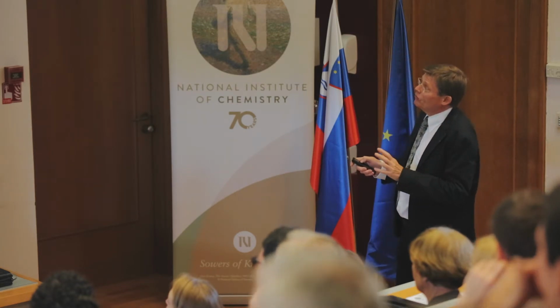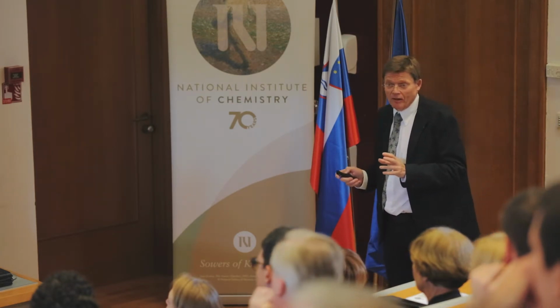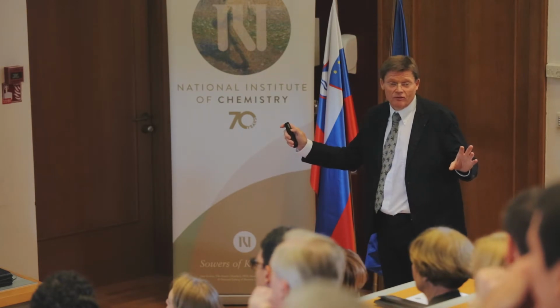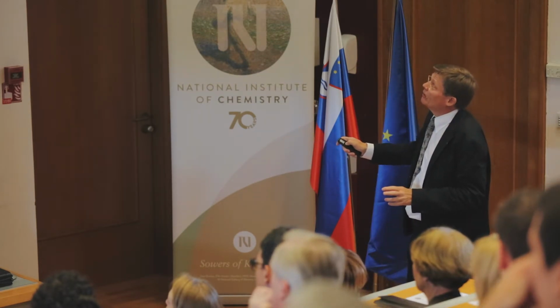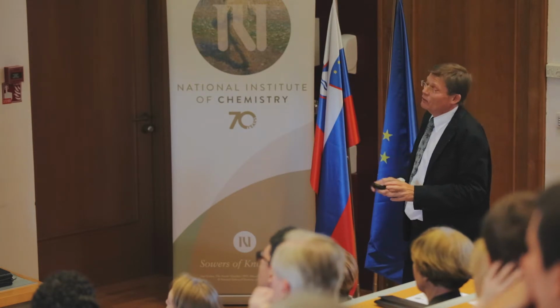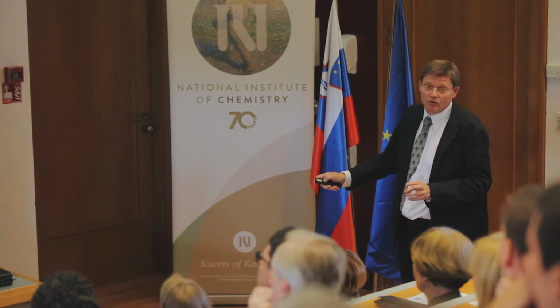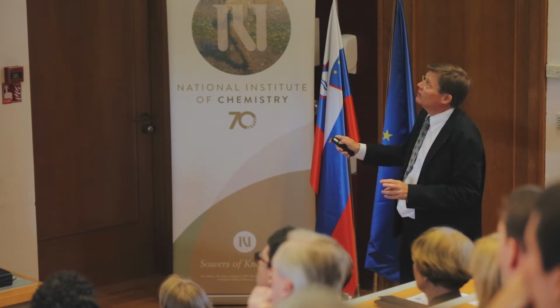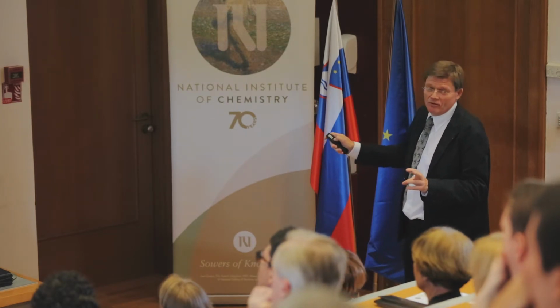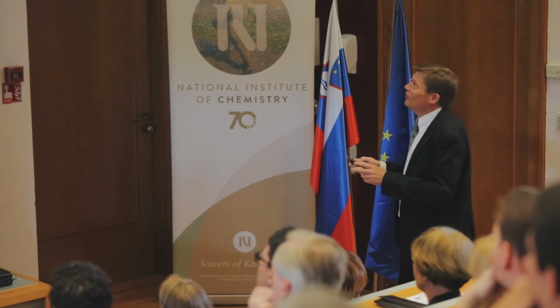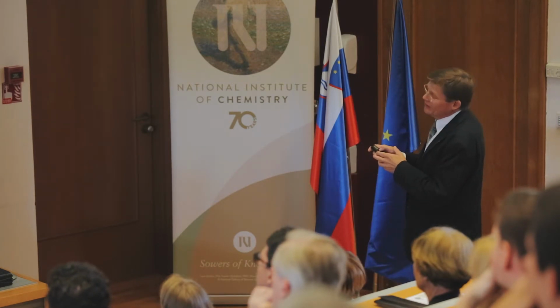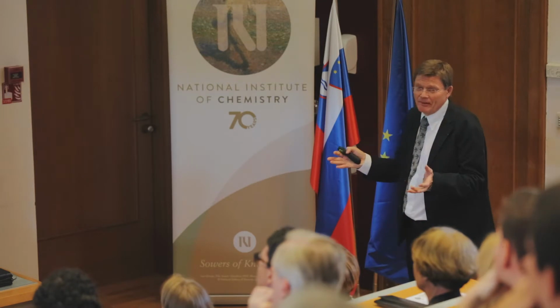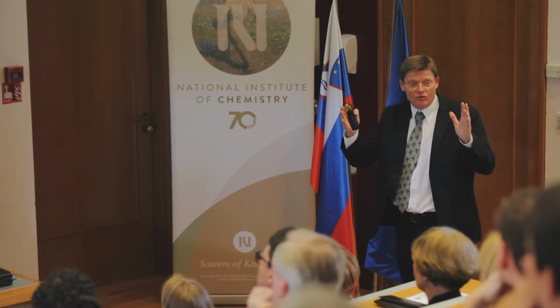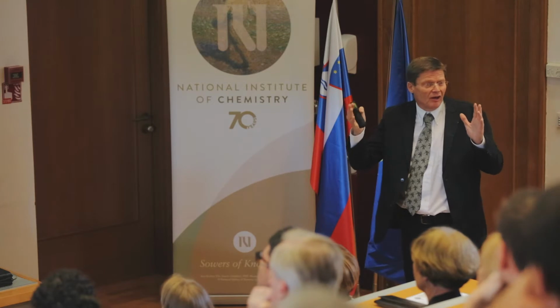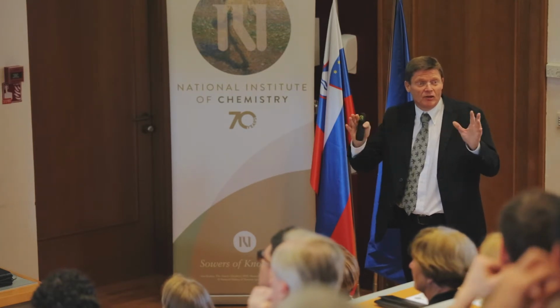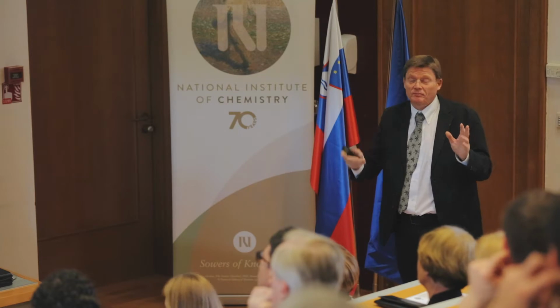So what would you expect in terms of impedance spectroscopy? At very high frequencies, you don't see interfaces. You would see the bulk semicircle. At lower frequency, you would see this kind of interfacial effect. This fits very nicely. But now there is a third one. This third one, you see, starts with 45 degrees. You would think, oh, this is polarization because of the electrodes. But the electrodes we are using are completely reversible. There's no doubt, and it would not fit.